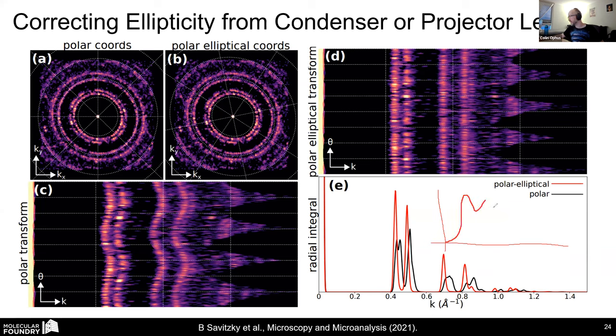You'd create a distribution as a function of r, where you have your reduced radial distribution function, g of r, your probability here, asymptotically approaching one, where this is the constant density of your material. And so this curve I've drawn is what radial distribution function or short range order mapping would give you in an amorphous material if the specimen is thin enough, right? And if you look at the pattern I'm showing here, this crystal material, you'd get something much sharper because your Fourier components go out much further. So you'd actually pick up a lot of your crystalline scattering out to very, very high angles. And then a fully liquid sample might give you a radial distribution function with a single maximum and then just flat after that.